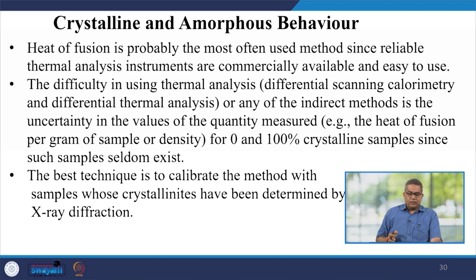The difficulty in using thermal analysis like DSC, differential scanning calorimetry, or DTA, differential thermal analysis, or any other indirect method is the uncertainty in the values of the quantity measured for a 0 to 100% crystalline sample, since such samples seldom exist. So, it is very rare to find such a reference sample. The best technique is to calibrate the method with samples whose crystallinity has been determined by XRD.